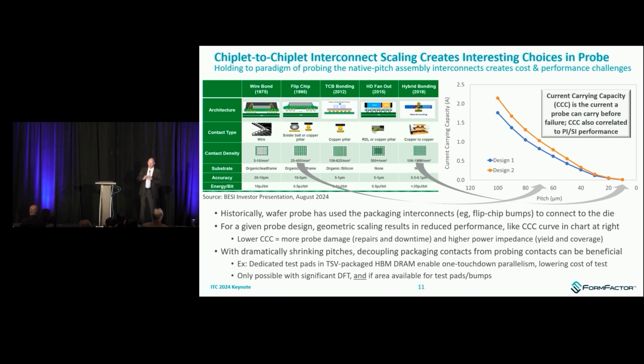And there's two places where I want to focus on. Remembering that probe has typically been done through these packaging contacts. And the fourth line from the bottom, contact density. For wire bond, easy, right? Big pads, spaced far apart, easy to contact. And this has always been the way, for example, microcontroller test is done, or DRAM test. You use the bond pads as the contact points. You've got to be a little bit careful with where you touch them and that sort of thing, but it's not an insurmountable challenge. Move through things like flip chip. So flip chip, and I'll connect this to the chart on the right in a second, lives at somewhere around, at least in the most challenging configurations, this 75 micron pitch I referred to. Our example of a state-of-the-art probe card in SoC or logic is right around this level. And that's something that could be done fairly effectively, fairly cost effectively.